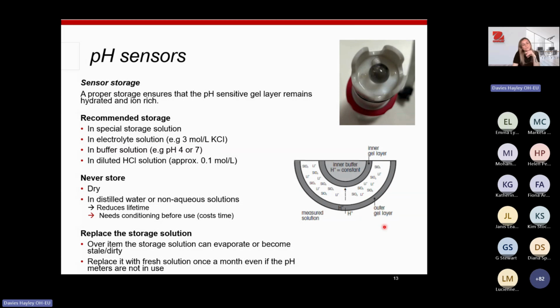Never store in distilled water, or in non-aqueous solutions, because that will just reduce the lifetime of your electrode. If you've allowed your electrodes to get dry, so you found one on the desk the next day and it's gone dry, we can recondition them. I will go over some tips on how you can recondition the pH electrodes before you write them off. So never store them dry, never store them in distilled water. It needs to be in this nice ion-rich solution.